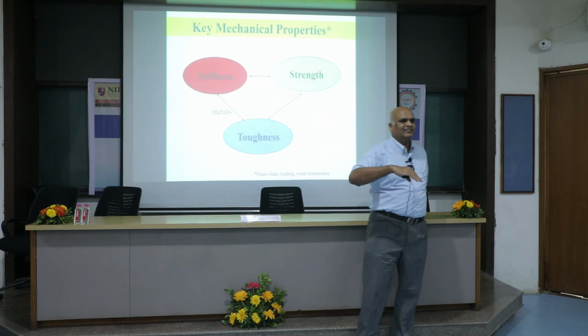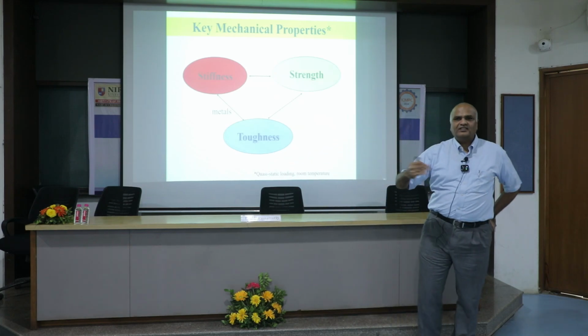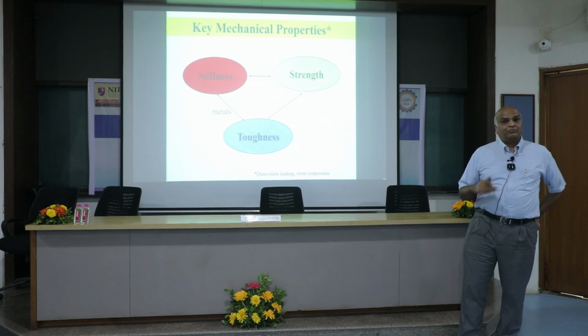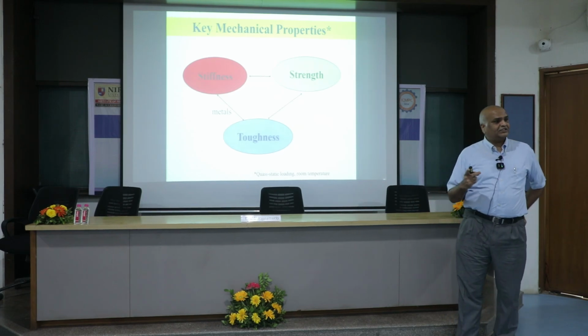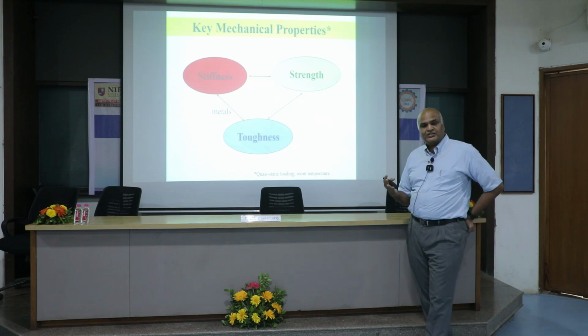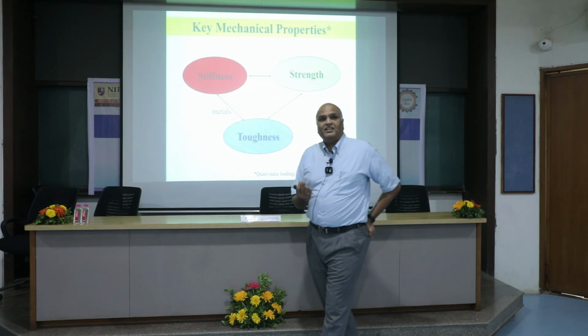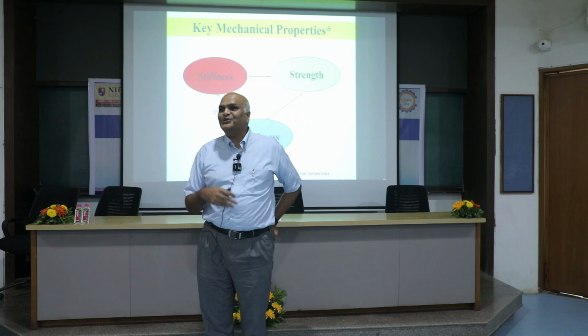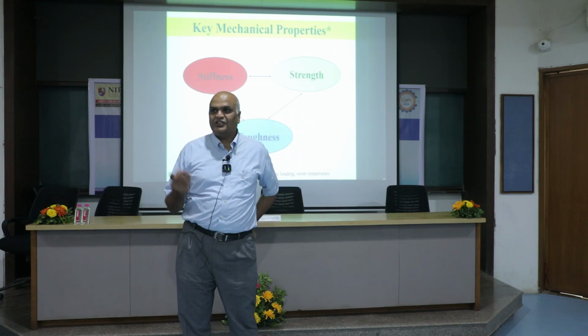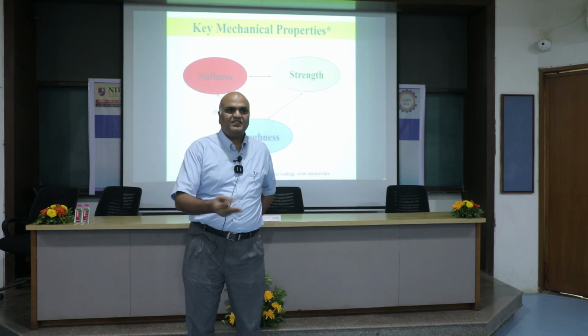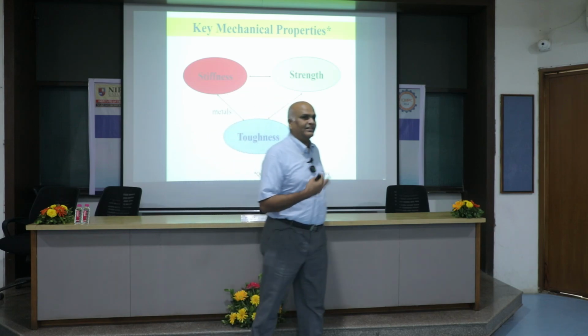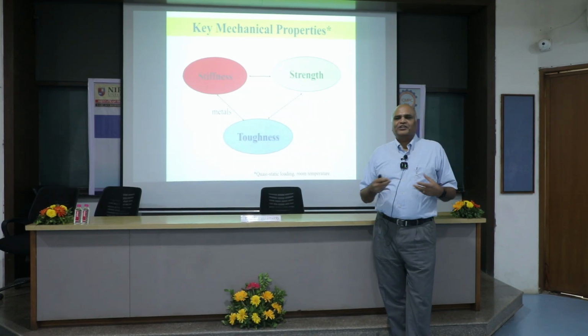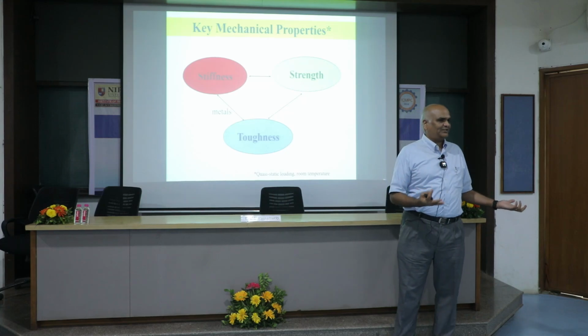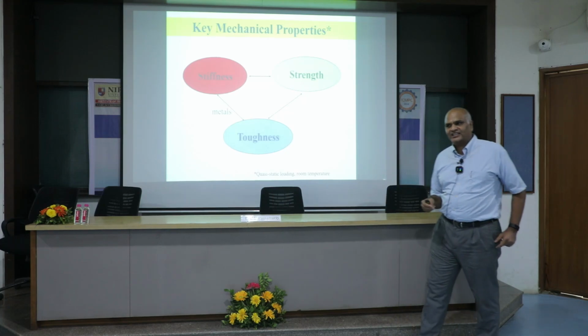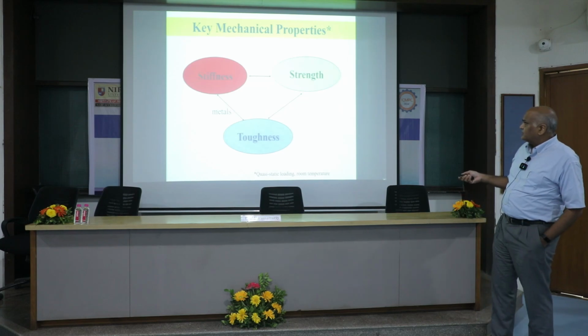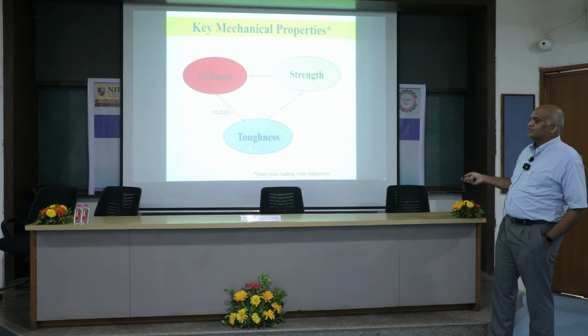So you take ceramics, they are strong, they are stiff, brittle, right? Metals, pure metals, their stiffness is very good, the toughness is very good, but strength is poor. That's why pure gold, you don't use it. You alloy it with copper. You don't use 24 karat gold, 22 karat, because copper will strengthen the material, increase the hardness, so that your jewelry and all don't wear off very fast. This precious metal, right? That's why you use 22 karat gold. So the thing is, we play with strength and toughness combinations there.